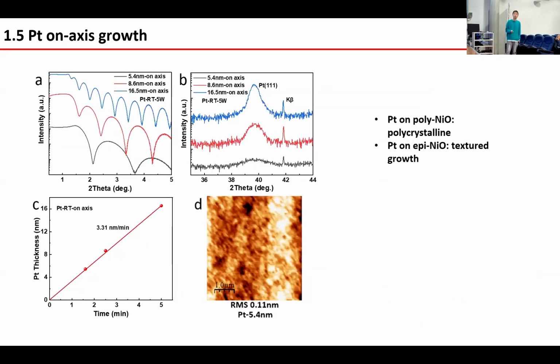And finally, I will grow platinum on-axis at room temperature. Here shows growth of a series of thicknesses, and the peak shows a very identical platinum peak. Then we also calibrate the thickness versus sputtering time and get the deposition rate again. And also a relatively flat surface is obtained from the AFM image. One thing I need to mention is that the platinum grown on the polycrystalline nickel oxide structure will be polycrystalline, while the platinum grown on epitaxial will be a textured growth.